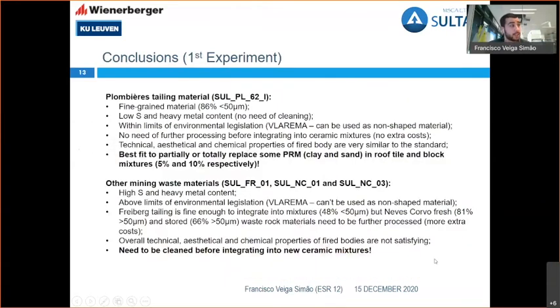The conclusion is that indeed the Plombières tailing material is a fine-grained material, with low sulfur and heavy metal content within the legislation. And to note, as I mentioned at the beginning in the material section, they didn't need any further processing before integrating straight into the mixtures. This means for a company no extra costs and really good suitability to integrate. Of course, as mentioned, the technical, aesthetical, and chemical properties in general were very similar to the standard with the Plombières tailings mix, and it is definitely, out of all these assessed materials, the best fit to partially or totally replace some of the primary raw materials such as clay and sand in the roof tile and block mixtures.